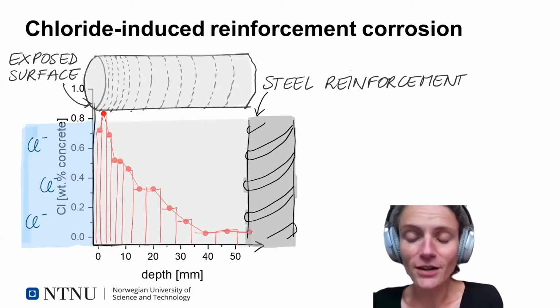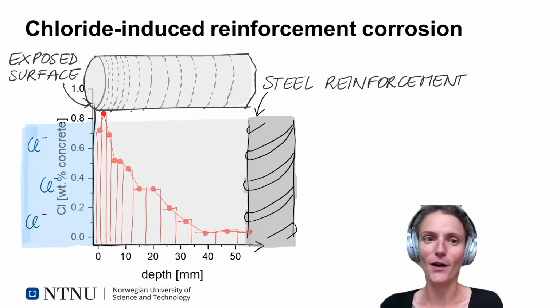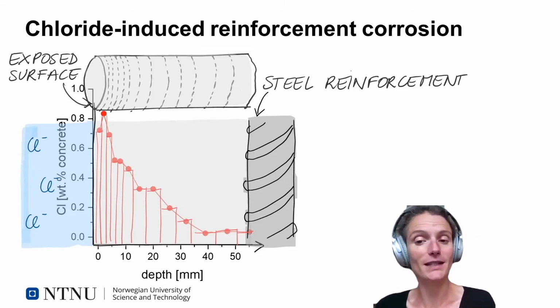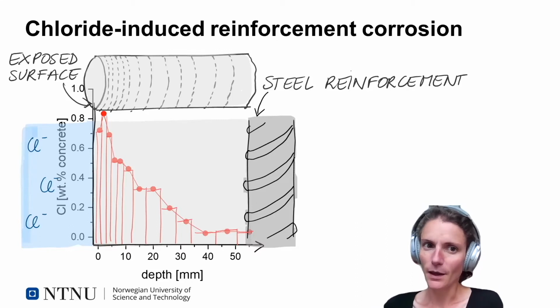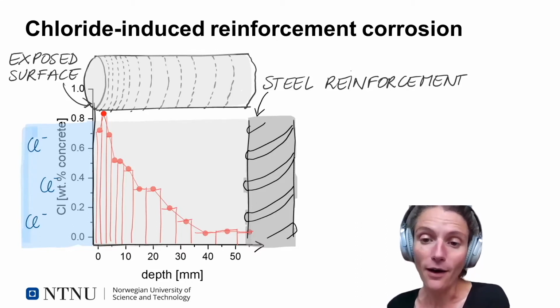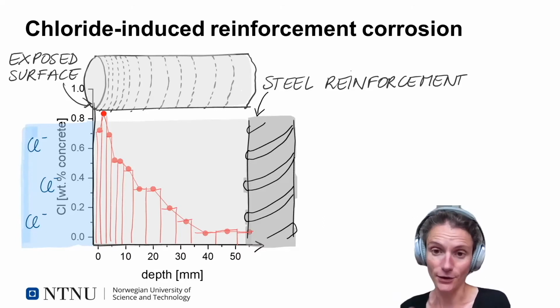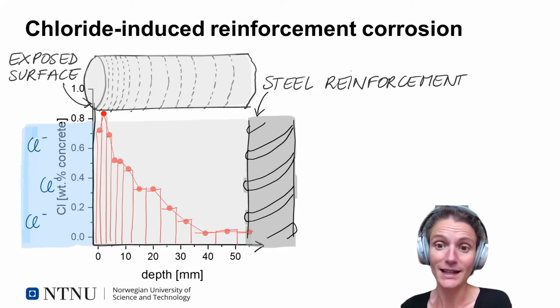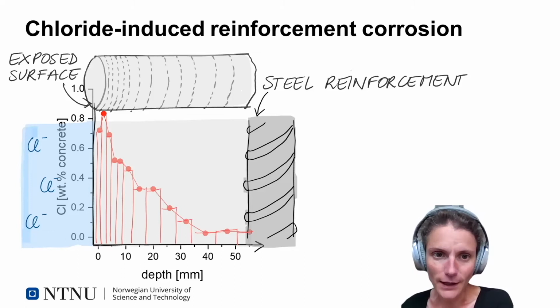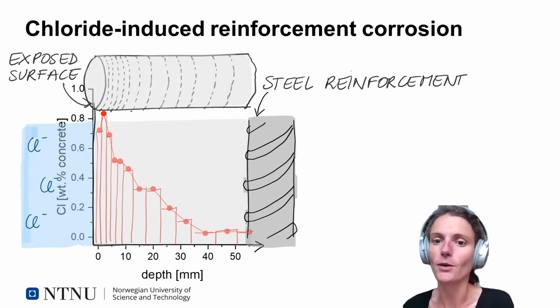Imagine you're an engineer and you're responsible for the maintenance of a reinforced concrete bridge, which is exposed to chlorides. One way you can figure out how far the chlorides have penetrated into the concrete cover is by extracting a concrete core, profile grinding it, so you get dust at different depths from the exposed surface, and analyzing this concrete dust for its chloride content. If you then plot this chloride content as a function of the depth where you've collected the dust, you get a chloride profile, as you see here.